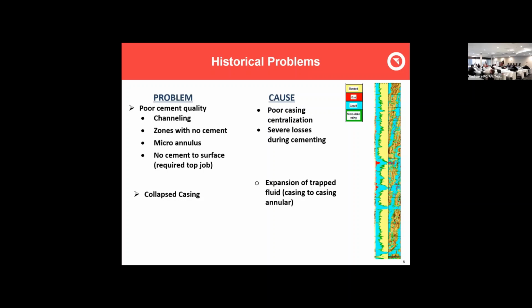I think a lot of what we've discussed is kind of long-term effects of cement bond, all these things. Really, one of the main things that we focus on is placement of cement. And one of the biggest ones, really, if the placement's wrong, or if you have channeling, if you have free water within that casing to casing annulus, you can lose your well the first time you flow it. You can collapse it that first time. So that's something that we take very seriously. That's part of the reason why we've been doing these two-stage jobs.